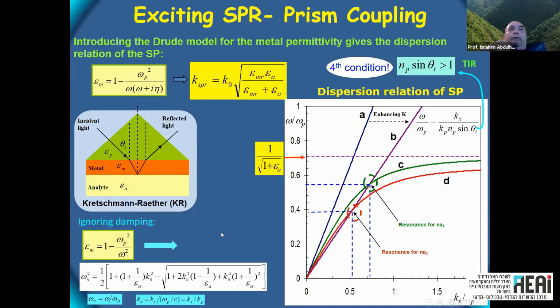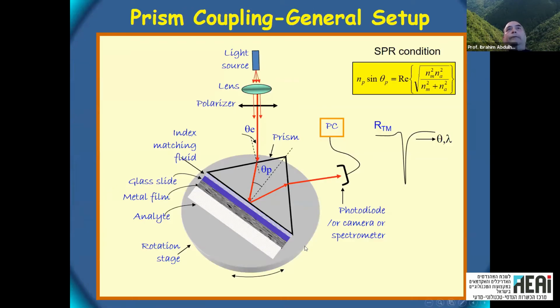Okay, so we get this shift, and what we measure is actually the whole curve, the spectral curve or angular curve. Now we can measure the angle or wavelength or intensity. There are many modes we will talk about. Experimentally, it's a very easy setup. You can have the thin film on top of a prism, and then having a collimated light and varying the angle and measuring the reflectivity with a photodetector if you want angular mode, or spectrometer if it's a spectral mode. So you look for the resonance in the wavelength or angle and look for variations of the shift of this resonance with the refractive index of the medium here.